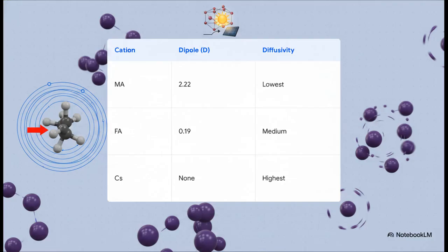So the crucial point is, how do we actually control this? How do we stop our solar cells from rearranging themselves every single time the sun shines? The answer lies in those A-site cations we looked at earlier. Comparing these specific cations tells a really clear story. Methylammonium, or MA, has a very strong dipole moment of 2.22 debyes. It basically acts like a heavy magnetic anchor. Its strong dipole shields the electric field and locks the surrounding iodide ions in place, which leads to very low diffusivity.